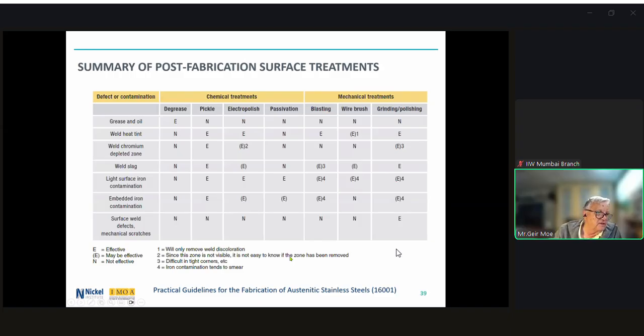But here we also have a table that summarizes the effectiveness or non-effectiveness of various chemical and mechanical treatments to remove various types of surface defects or contamination. For example, grease and oil can only be removed by a solvent or caustic solution. Heat tint can be removed by pickling and mechanical treatments, yet is still corrosion resistant enough to be immune to removal by a passivating solution. Again, this table can be found in our Practical Guidelines for the Fabrication of Austenitic Stainless Steels, publication 16,001.